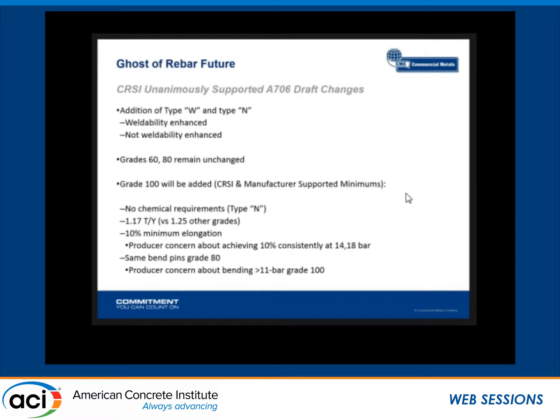So this is the CRSI unanimously supported draft to A706 to include grade 100. This is type W and type N. Type N's a placeholder. Grade 60 and grade 80 remain unchanged. Grade 100 is added, and these are the basic properties that we believe we can support, and this was a unanimous resolution out of CRSI's Material Properties Committee. That was a 1.17 ratio, 10% elongation. There was some producer concern about hitting 10% consistently at 14 and 18 bar, and then we're keeping the grade 80 pins. There is concern about bending anything bigger than an 11 bar.